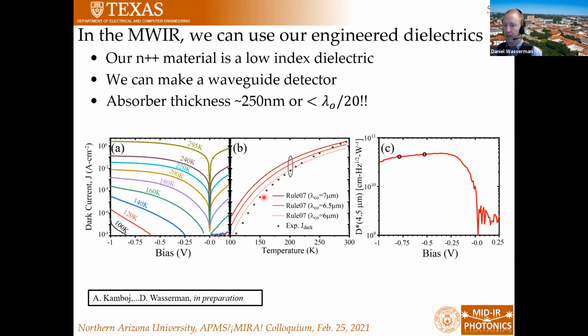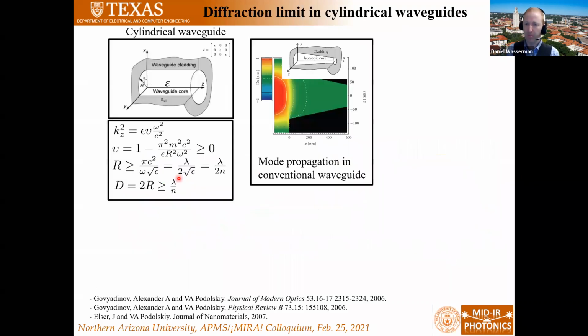So if you look at the comparison to the rule of 7, which is the rule for dark current that people use, that says that this is the state of the art that you could get for a commercial detector. We're below that, in some cases by an order of magnitude below that, and about 2 orders of magnitude below what you would typically get for a detector with that sort of efficiency in this material system. And again, D stars in the 10 to the 10 range, and this is at 200 Kelvin. So we're operating at what is a pretty hot temperature for an infrared detector.